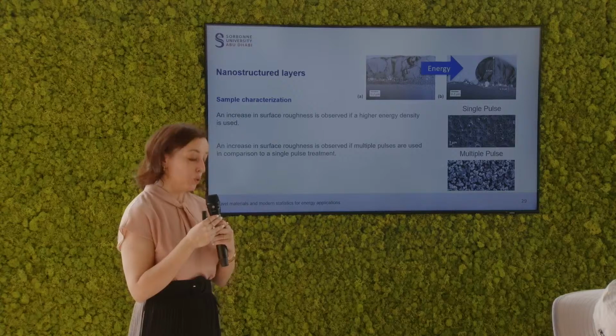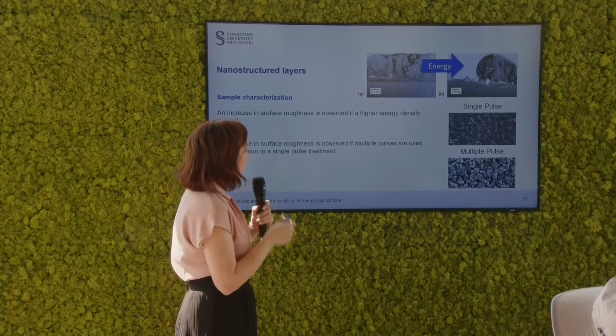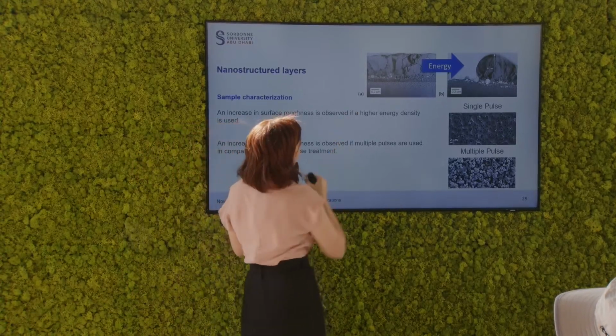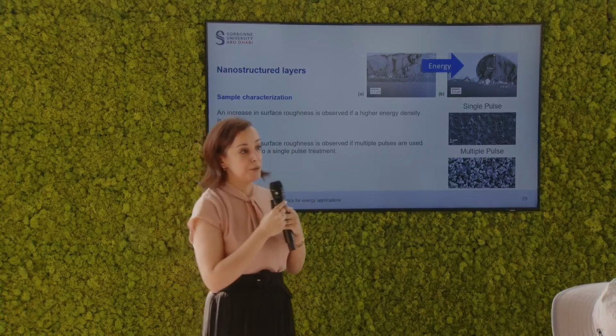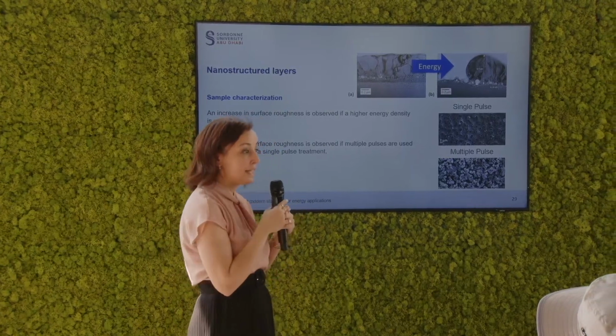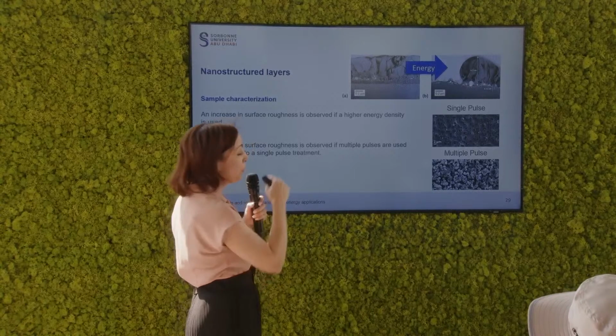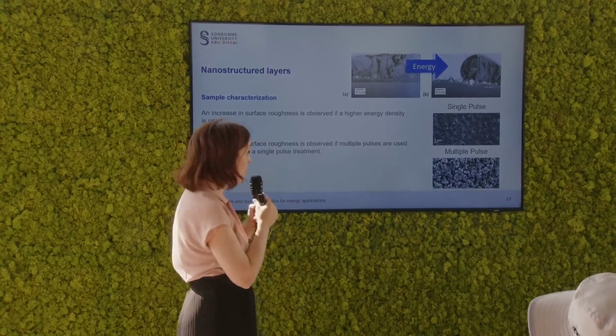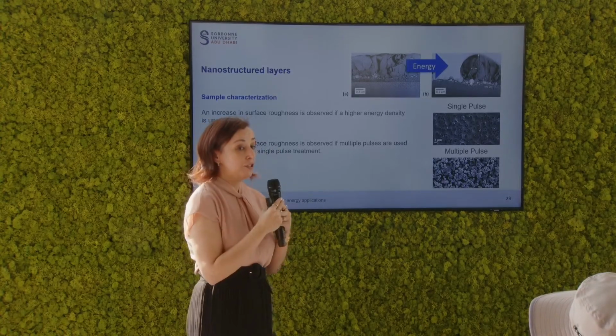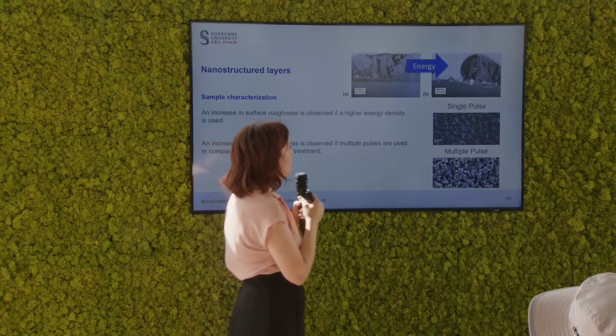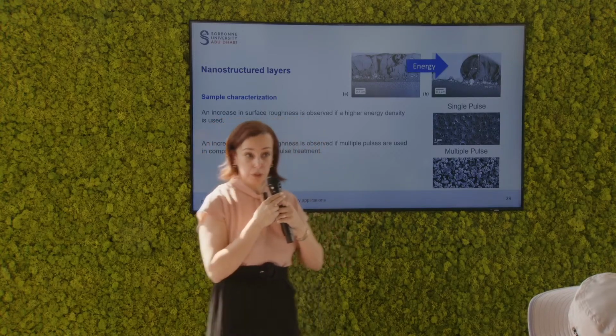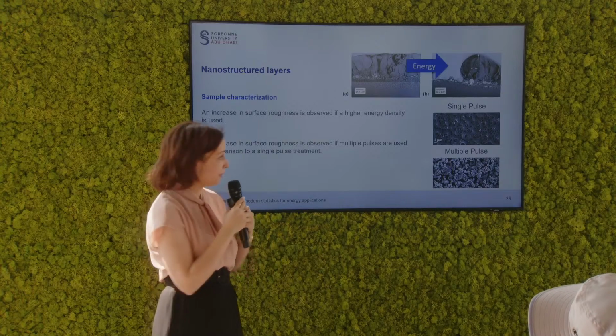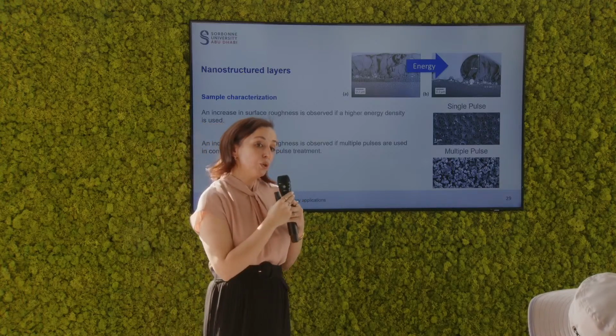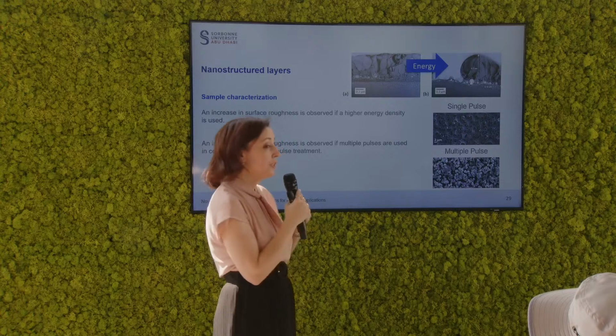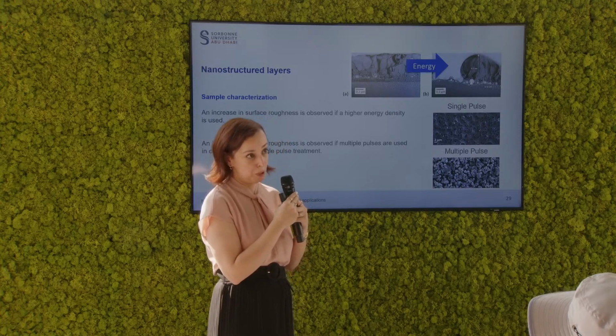And you can control that amount of surface roughness. So the image here that's labeled A on the left shows you a very smooth laser annealing process where you don't have a lot of surface roughness at the top. However, if you increase the energy of that laser pulse, then you generate a larger amount of surface roughness on the surface. The other way to control the surface roughness is through the use of single pulse or multiple pulse.